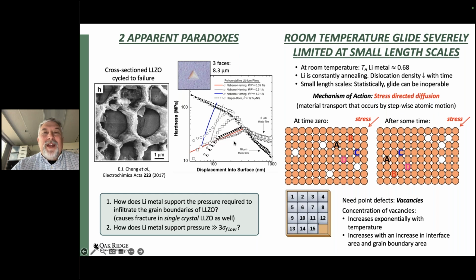The bottom line, the key takeaway, is that when dislocations aren't available within that stressed volume of lithium, then glide becomes inoperable. So we take that mechanism away, and the lithium has to find some other way to alleviate the pressure. One way to do that is through stress-directed diffusion, and that diffusion is going to be driven by the gradient in the elastic strain. Basically, it's that non-uniform compression of the lithium's lattice parameter. We talked about shoehorning more and more lithium into these morphological defects at the interface, so that's what produces this gradient in strain.